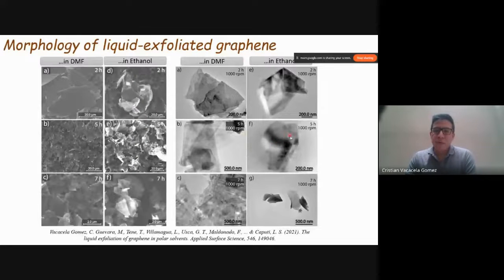Of course, if you compare picture B with picture F, we can see here darker regions, and the layer-by-layer structure is not observed when we exfoliate graphite in ethanol. So the best from this result, very simple, is that the best solvent to prepare graphene, at least in this result or in this paper, is dimethylformamide.